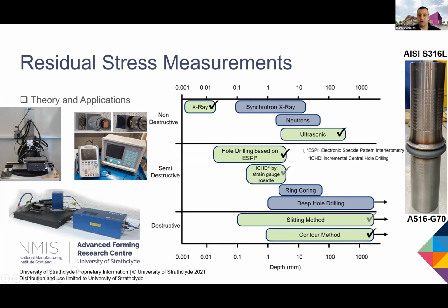We have also recently developed quite a lot of technique around ultrasonics, which is non-destructive and allows us to measure surface, subsurface, and bulk stresses, obviously averaged through the depth that we are applying the method, but it is still a very valuable piece of information. For this specific work, since we were going to do characterization, our go-to method was the contour method. Anything that is going to be sectioned, we would like to look at that cut face and measure stresses and get a full cross-sectional map of the stresses acting at that face.